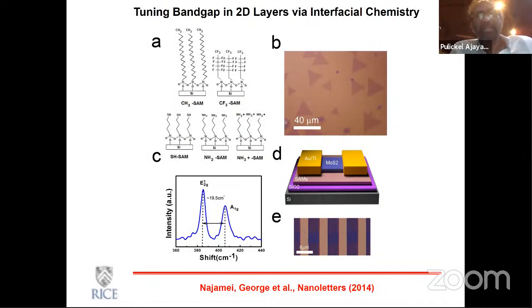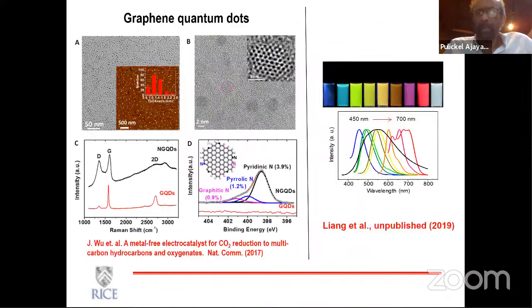Or you could also attach functionalities to the surface. Example of self-assembled monolayers being added to the surface of some of these layers, which change the electronic structure. So you can also modify it by simply adding acceptor layers or donor layers onto the surface. And if you do harsh chemical treatments, these kinds of structures break down very easily. And we've also been looking at how nicely you can break up these two-dimensional layers into quantum dots and quantum disks, maybe, because they are two-dimensional in nature.